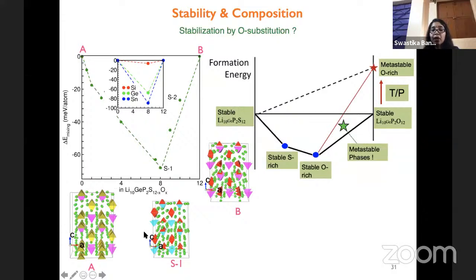So this particular composition, which is the most stable, has the phosphate in it and GeS4 tetrahedra as the sulfide counterpart. So this is a mixed oxygen sulfur framework, which is very stable, even more stable than the parent compounds like LGPS and LGPO. And we can actually think that it could be a potential candidate in terms of synthesizability, because in terms of thermodynamic stability, they are